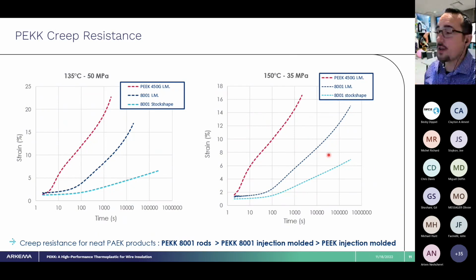The same trend is true, exaggerated a bit here at 150 degrees C, where we have a higher creep performance, consistent with our higher temperature stability versus some of the other PAEK materials.